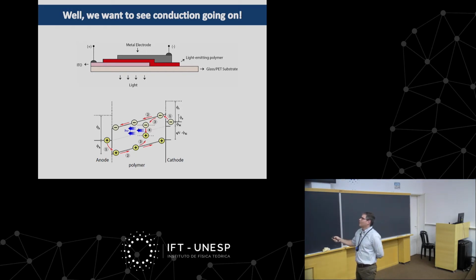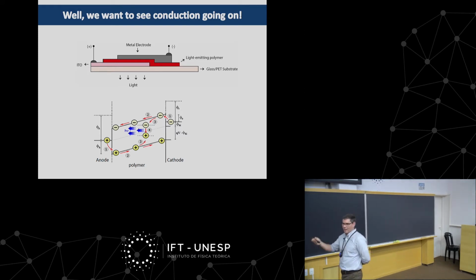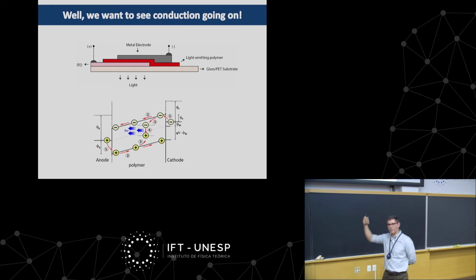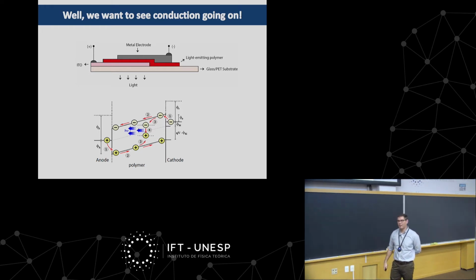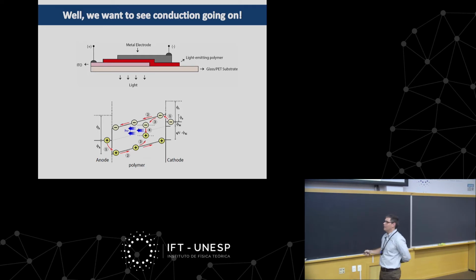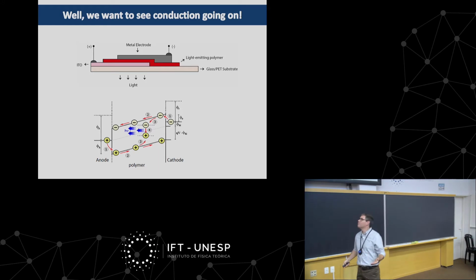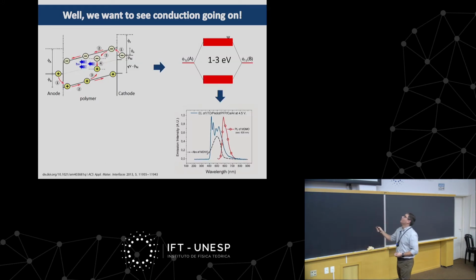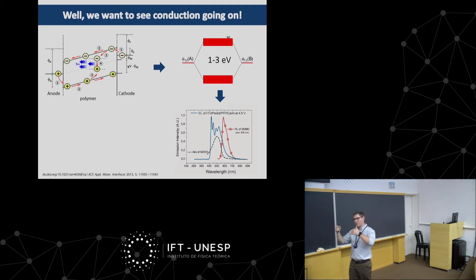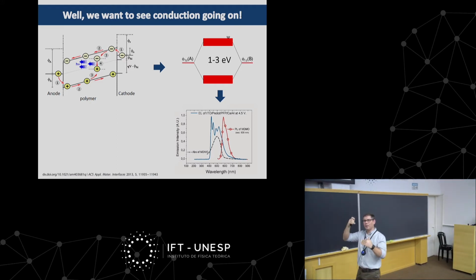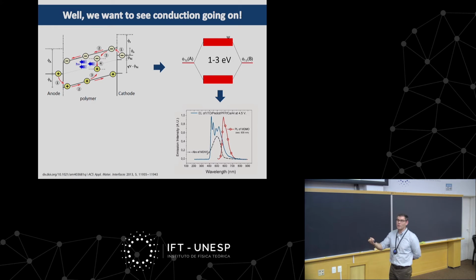And those two charges are conducted through these two bands, conduction and valence band. And at some point, they can meet each other. So you have an electron and a vacancy of an electron. Of course, that electron will want to relax into that vacancy. So it relaxes back to the vacancy on the valence band. And for that, it has to release some energy, and it releases that energy by shining some light, right? And because you can pick the energy difference between the band gap and the valence band to be in the visible range, you can have a spectrum that emits in colors that we know as visible light.